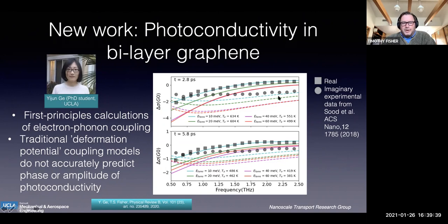I could show you what the previous modeling produced, which was a semi-classical Boltzmann transport theory modeling, but it's too far off the graph to show. And so we were able to use the same kind of multi-carrier coupling concepts, in this case light, and actually this has light and electrons and phonons because there's the phonon electron scattering model baked into this, that produces a physically accurate result that's accurate spectrally. I think that's important too. Like most people, if you measure photoconductivity, you just shine light on it, probably broadband light, and see how the conductance changes. But this shows that you can do that on a spectral basis as well.